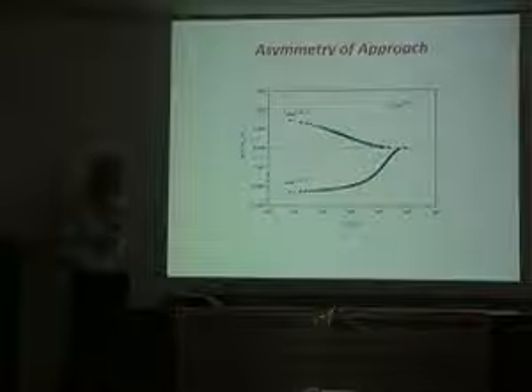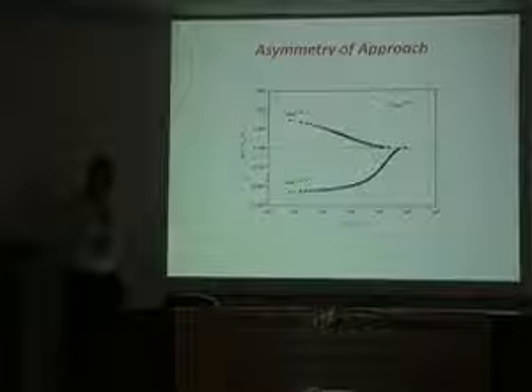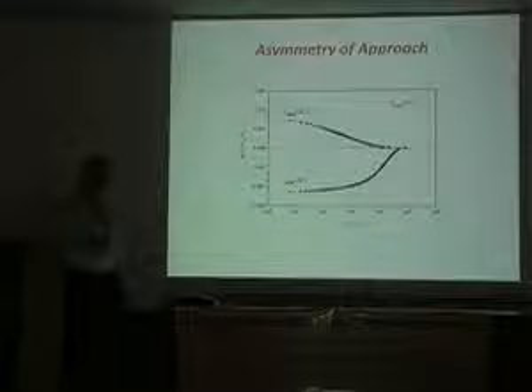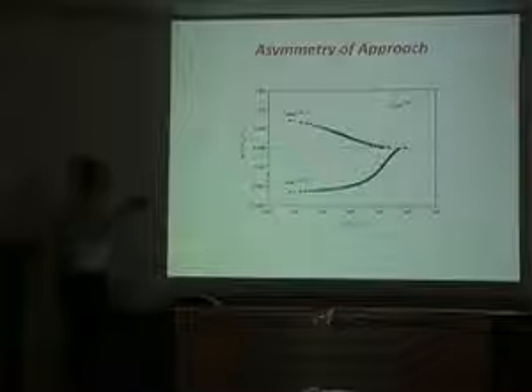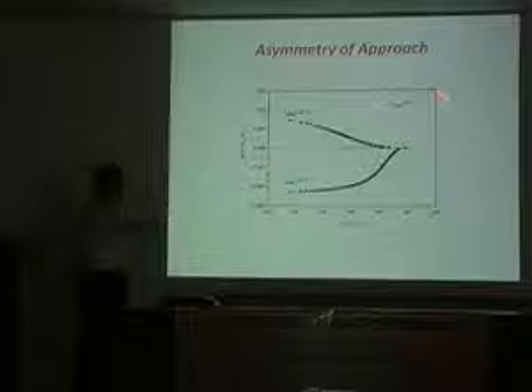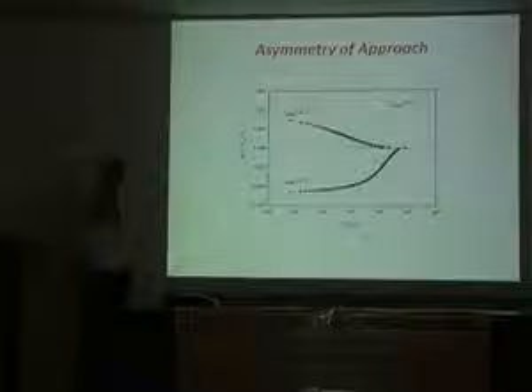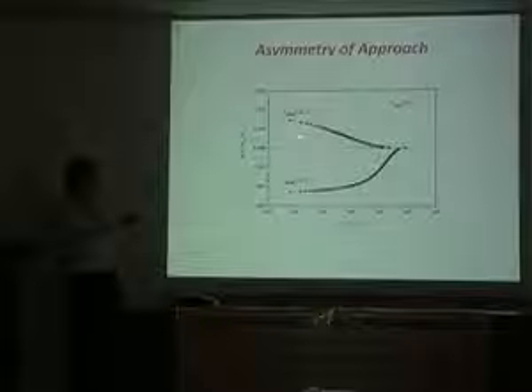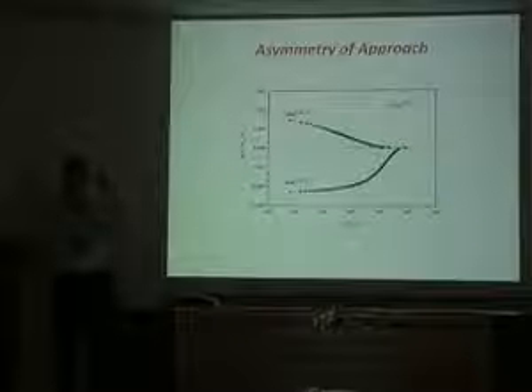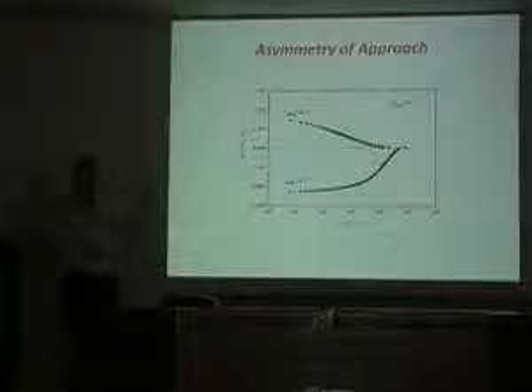So I just want to, maybe you're going to say this, but if I didn't want to think in terms of free volume, right, could I just simply say that when I start at the high temperature, my relaxation time is smaller? Yes. And that's what's going to show up? But this curve and this curve are all at 35 degrees. Right, but effectively... Well, this is what people think of as the fictive temperature, right? So this one will have a higher fictive temperature than this one, right? And the corresponding relaxation time will, to a first approximation, tell me how fast it is, and when I get to the models, you'll see that they're equivalent, okay?